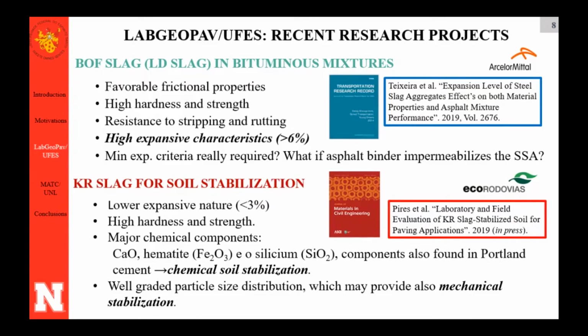It's usually lower than 3%, so it's ready to be used in pavement. But it's like a new slag in our state, because the process to get KR slag was recently added to the steel company. So we investigate the use of this slag for soil stabilization, because this slag has major chemical components that make possible this material have some pozzolanic reactions as cement. So there are many references that talk about the use of slag already as a cement material. They call slag cement, actually.